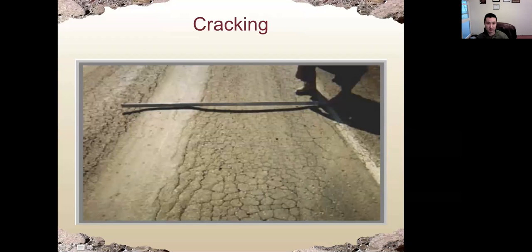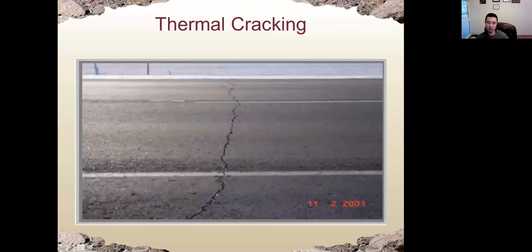This is the rutting caused by soft asphalt together with fatigue cracking. So if the fatigue cracking becomes too severe, part of the asphalt can be spalled off, and we have potholes. This picture has cracks which are perpendicular to the direction of the pavement. This is caused by temperature change, or thermal cracking.